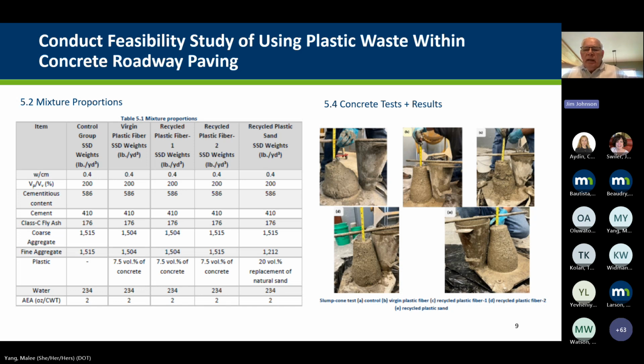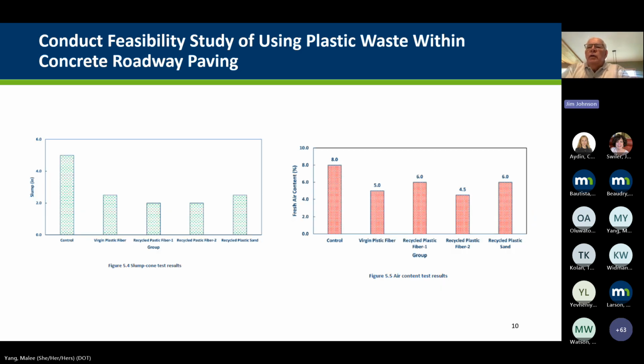Then please, Maylene, next slide. What I wanted to share with you, without going into great detail, on the left is the visual results of inches of slump that were pictured on that previous page. You can see what the results were for each of those batches or samples in terms of slump. To the right, there was an evaluation of air content, again on those same five samples, or mixes, I should say. And you see those results. Next page, if you would, please, Maylene.